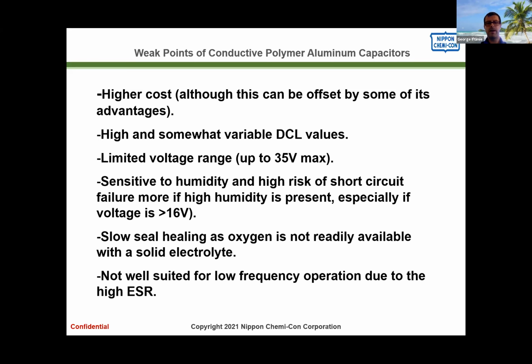Voltage range is limited to 35 volts. Again, that's primarily a design issue due to the polymer's weakness to humidity. We can have higher voltage polymers and they are available, but they are so weak to humidity that it's not really worth designing capacitors at those voltages. And then the other problem is that when polymers fail, they almost always fail as a short circuit, especially when you're talking about a higher voltage.